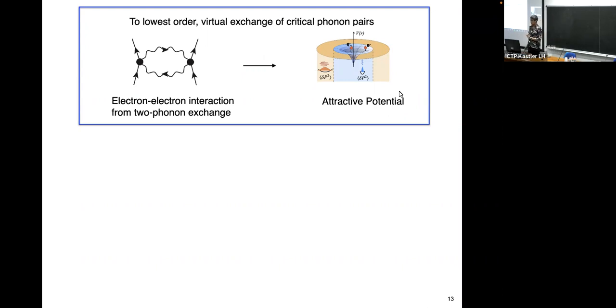In 2D, the energy fluctuations have an anomalous dimension. In fact, phonons are not well defined, but we can still talk about energy fluctuations. And as we'll see, they actually save us. We still have a Fermi liquid. So that's the best I can answer. Since this is less relevant in the RG sense than the standard Yukawa coupling, you would expect the vertex corrections to be small. Yeah, that was basically the argument, thank you, Sri. This interaction is irrelevant in the scaling sense, and so we don't expect the higher order to be important, but we haven't actually calculated it.